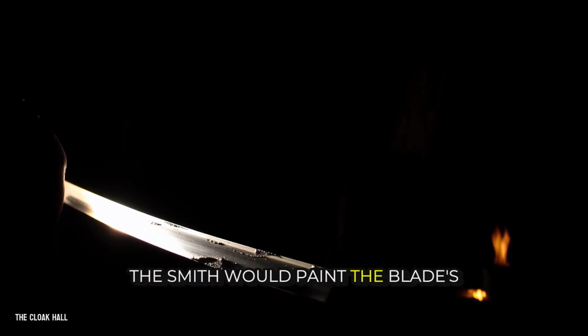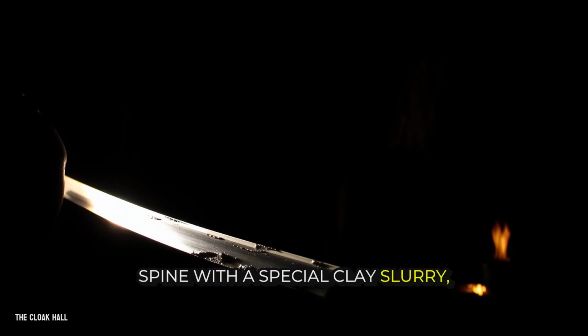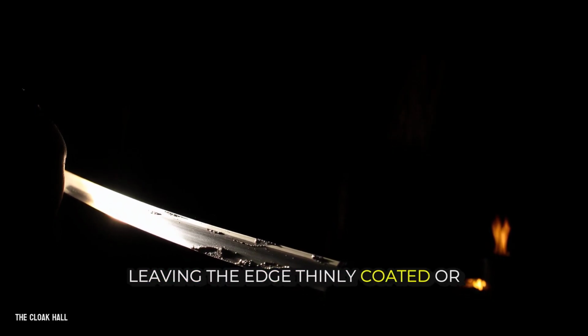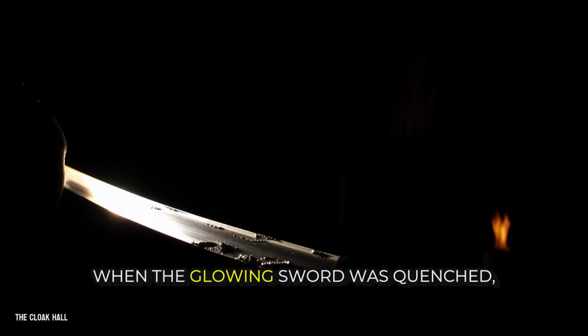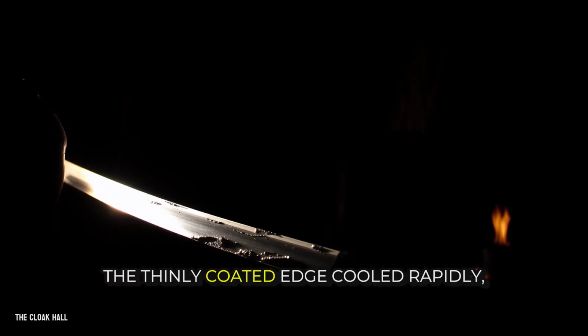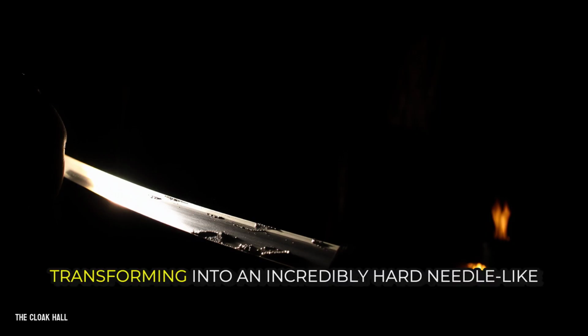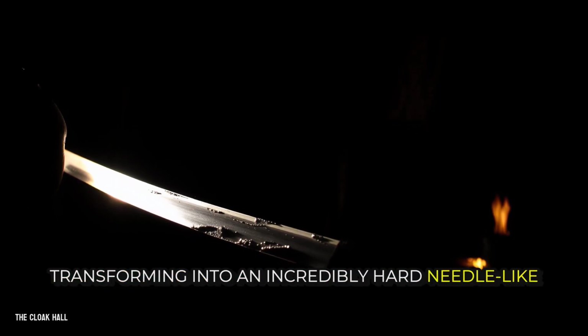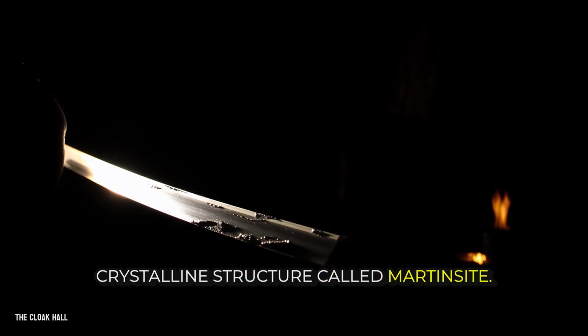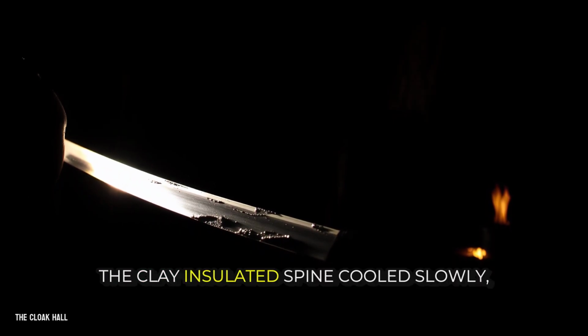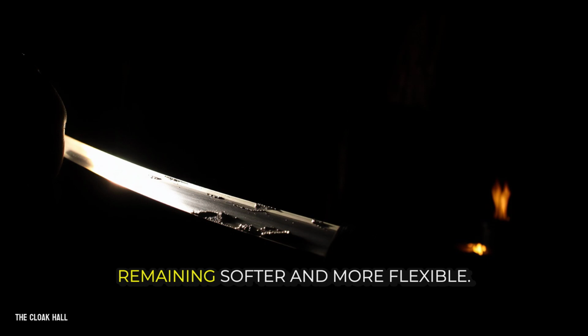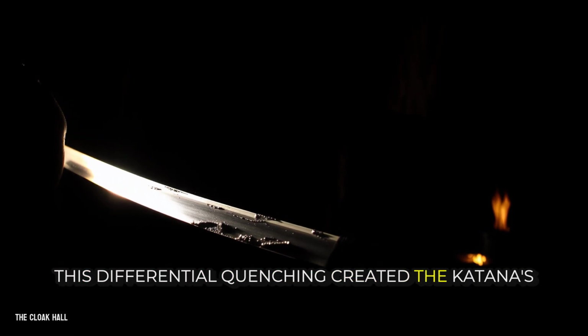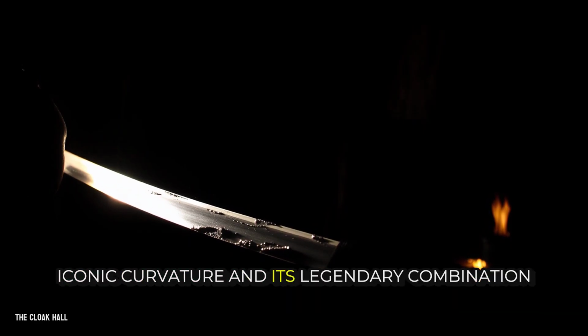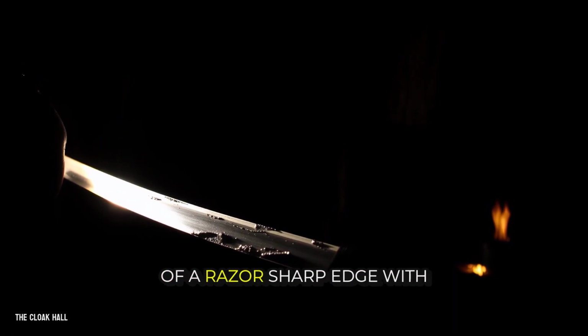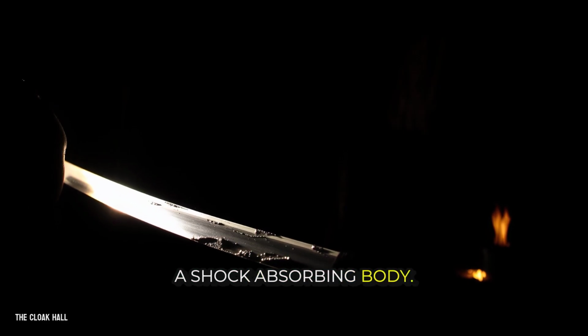The smith would paint the blade's spine with a special clay slurry, leaving the edge thinly coated or bare. When the glowing sword was quenched, the thinly coated edge cooled rapidly, transforming into an incredibly hard, needle-like crystalline structure called martensite. The clay-insulated spine cooled slowly, remaining softer and more flexible. This differential quenching created the katana's iconic curvature and its legendary combination of a razor-sharp edge with a shock-absorbing body.